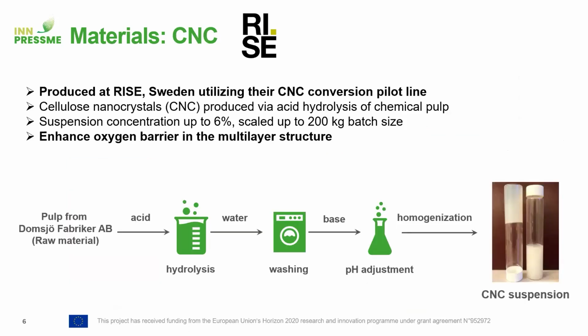Then the CNCs were produced at RISE, Sweden, using their CNC conversion pilot line. These are produced by acid hydrolysis, and the raw material for it is pulp, but RISE has also demonstrated that it is possible to use other raw materials, for example, side streams or waste streams, to produce these CNCs. They showed that they can have a concentration of up to 6 weight%, and the batch size was about 200 kilograms. And in this multi-layer, the CNCs were used to enhance the oxygen barrier of the multi-layer, so to prevent the food from spoiling.